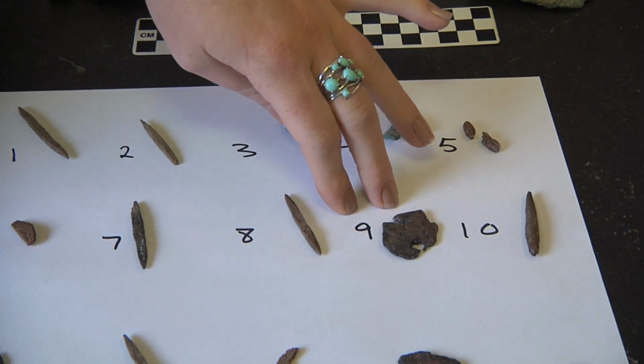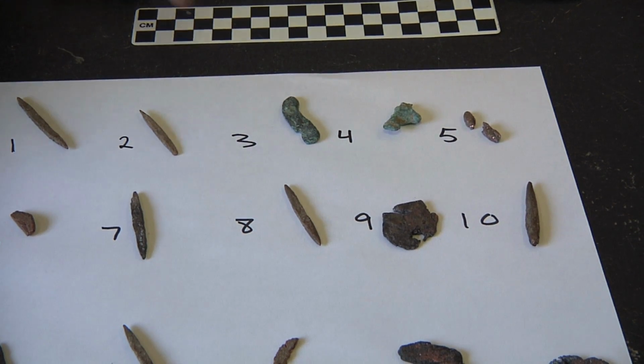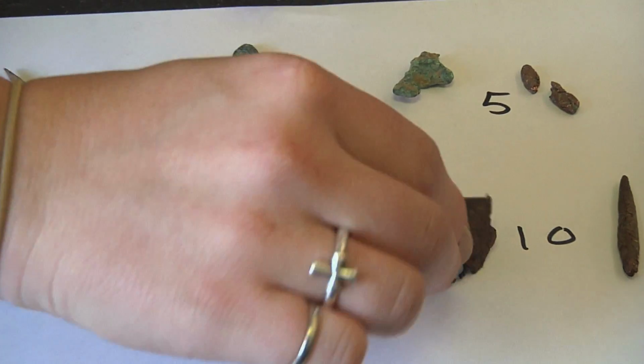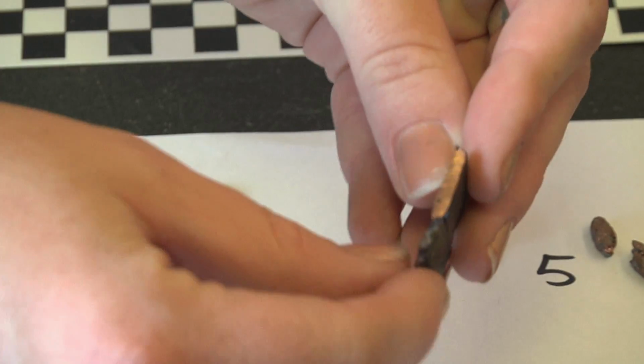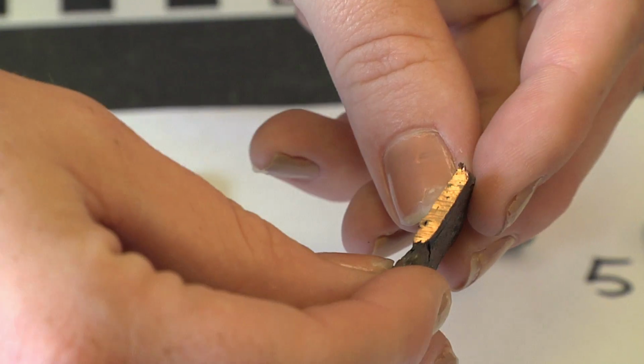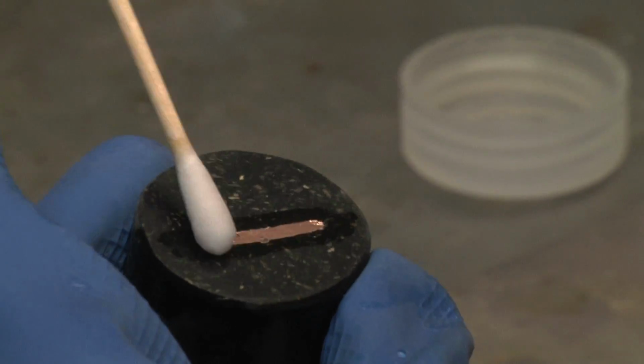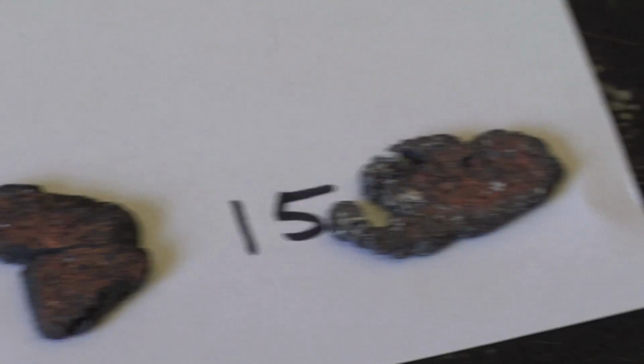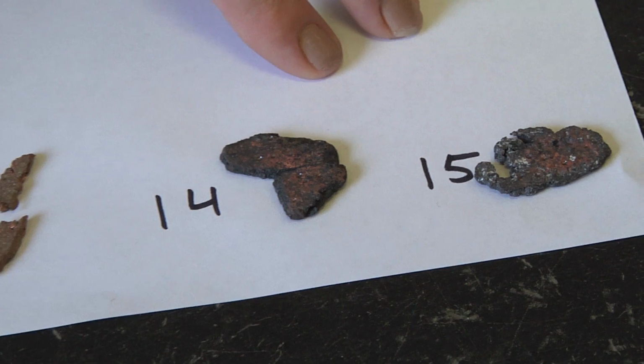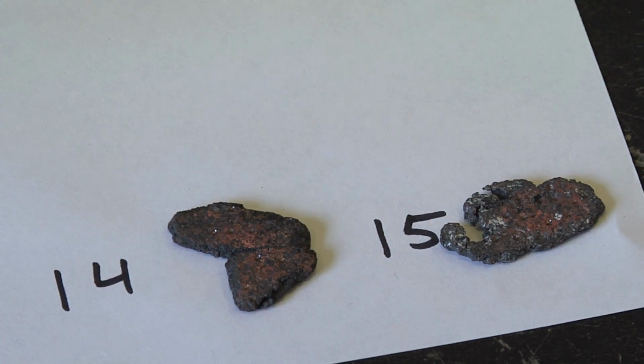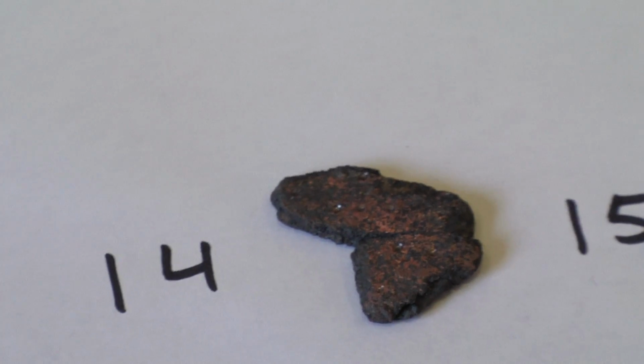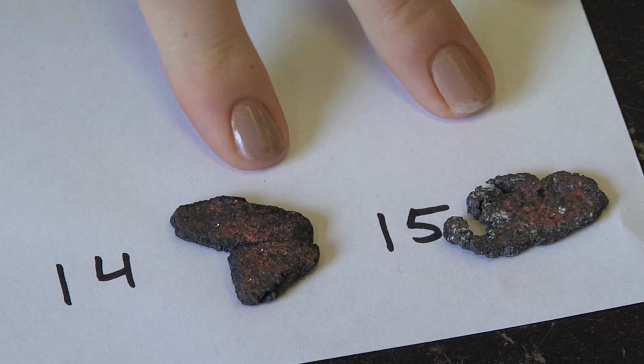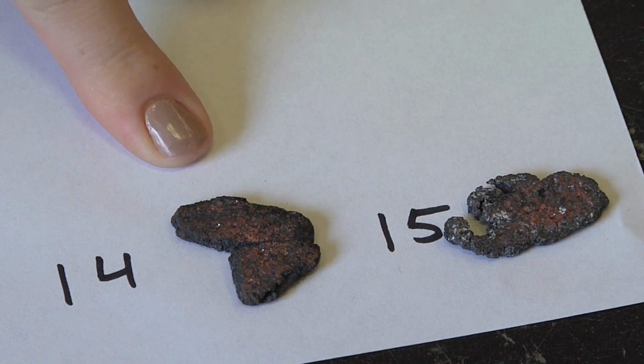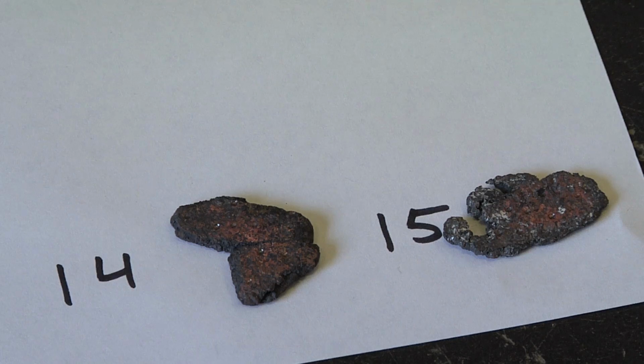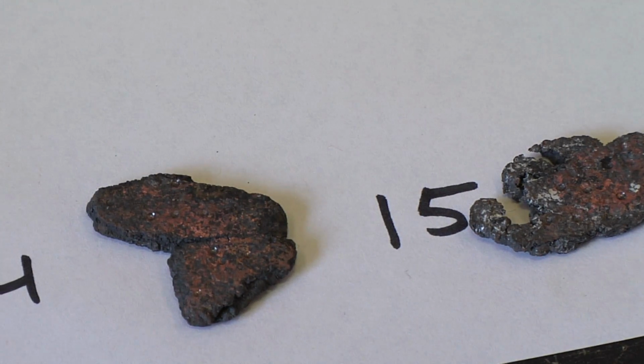We made a couple of sheets, as you can see here, for annealing purposes. They're easier to find in the fire than the awls were. Number 9, we cut off a sample here. As you can see, it's cut. We mounted and polished that sample for microstructural analysis. Number 14 and 15, you can see little dots on the interior surface of the samples. Those were from the hardness testing that we performed on the pieces. They were both annealed, but 14 was quenched, and number 15 was slowly cooled. So we did hardness testing to tell the difference between those two.